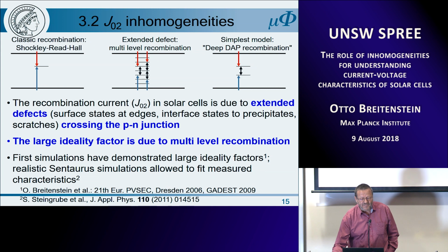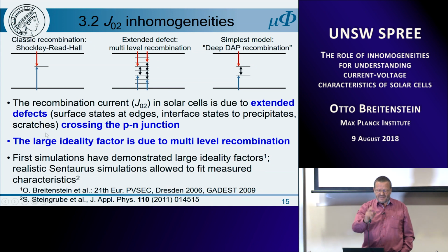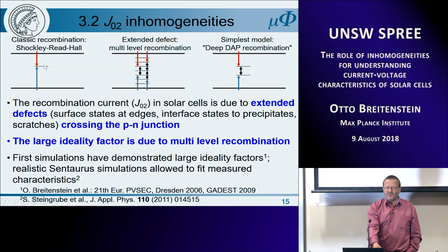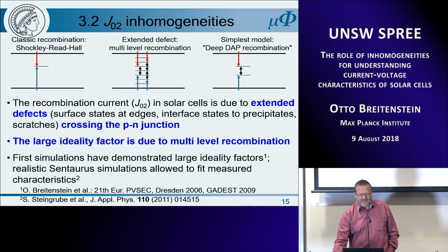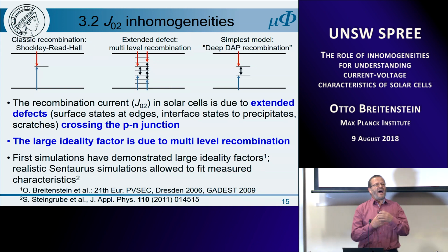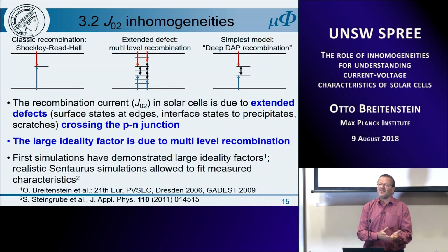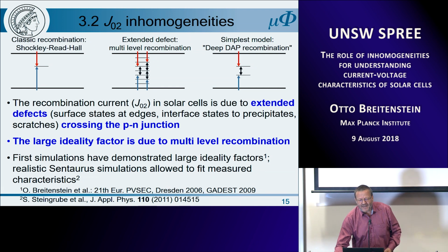Shockley-Read-Hall recombination means that we have one level and two steps. First the electron is captured, then the hole is captured. But at extended defects, we have such a high local concentration of defects that their orbitals overlap, which allows interaction between the levels. So we can have multi-level recombination as sketched here. The simplest model for multi-level recombination is deep donor-acceptor pair recombination. And this can easily be modeled, and that's what we have done.